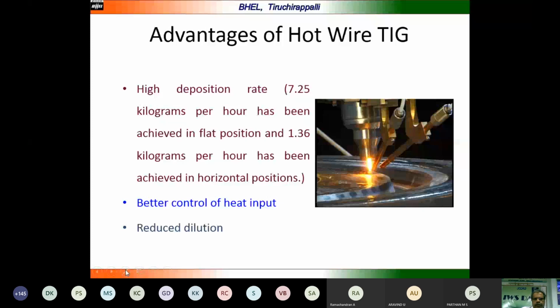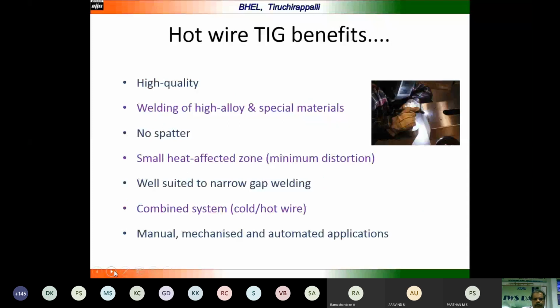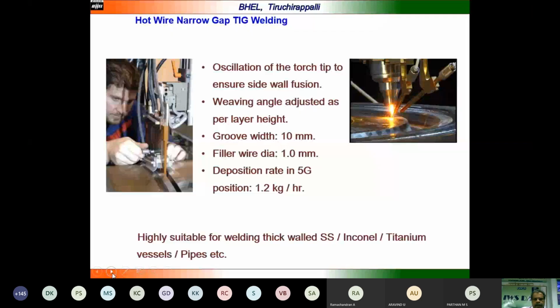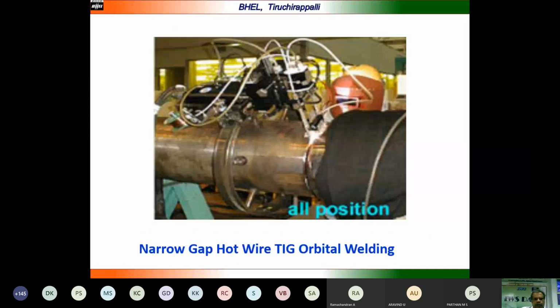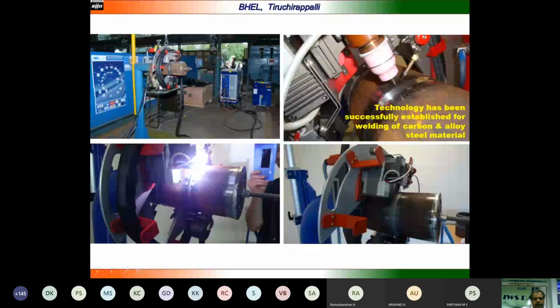And this is again the hot wire TIG welding process shown here, the narrow gap hot wire TIG welding process. As I told earlier, it is a hybrid variety of orbital TIG welding, narrow gap welding, and hot wire. All three are added together, and then pipes can be welded very easily by using this hot wire TIG narrow gap welding. What you are seeing is the application of a hot wire system here, and then the TIG welding, and then the wire feed is here, and this is a pipe in which the welding is performed by using the hot wire narrow gap orbital TIG welding process.